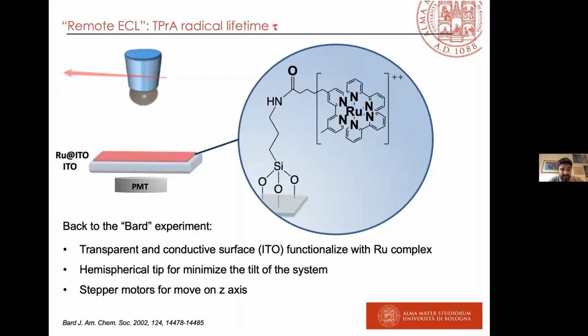Okay, so back to the Bard paper in 2002, where he demonstrated for the first time this mechanism. How did he demonstrate this mechanism? He used an ITO electrode, and he labeled the ITO electrode with ruthenium tris-bipyridine. And after he used a millimeter electrode with a hemispherical tip, and he moved this onto the modified ITO, close or at a higher distance from the emitting ruthenium layer, and it generates TPA radical and radical cation at the tip. In our group, we call this tip generation, surface emission mode.